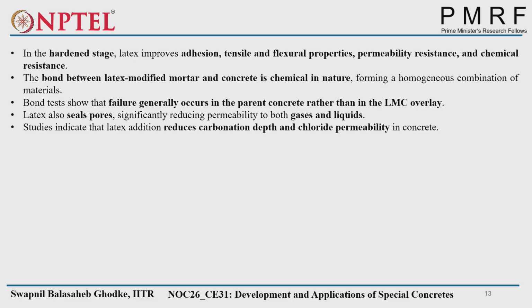It improves adhesion, tensile and flexural properties, permeability resistance, and chemical resistance. Now, you can say the bond between the latex modified mortar and concrete is chemical in nature, forming a homogeneous combination of materials. Very important here is that the bond is very strong, and it is observed that the bond has not been broken. The concrete is not broken at the bond; it is broken in the parent concrete itself. But in the first case, the polymer concrete, the bond is not that proper between the composite concretes. So here, latex modified concrete bonding is much stronger than polymer concrete.